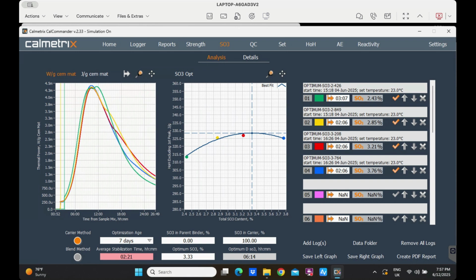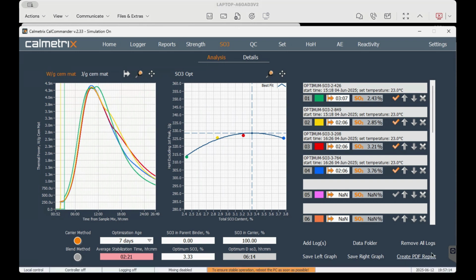Okay. Our next question from Muhammad is, and both Angel and Mujtaba, I will reach out to both of you on your questions, but a question from Muhammad: what is the minimum energy generated in joules per gram as per ASTM for OPC? I don't think there are benchmark values. There are benchmark values from different round robin tests. An OPC will generally give you, and you have to say at what curing, 72 hours or 7 days, around 320 joules per gram at 7 days. That's a pure OPC.